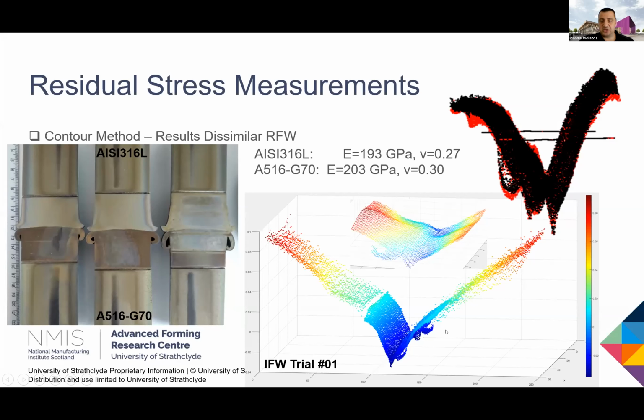If the overall view is a little bit too busy, we can focus on the actual welding region, and you can see how the different curvature exists between the two different materials. And that difference in curvature is what creates the residual stresses. Obviously, we scan both halves, we superimpose them, and we make sure that both halves are correct. You can see how nicely both of these halves are matching each other. That means that we have done a very good measurement, and that was the case for all three of our measurements.